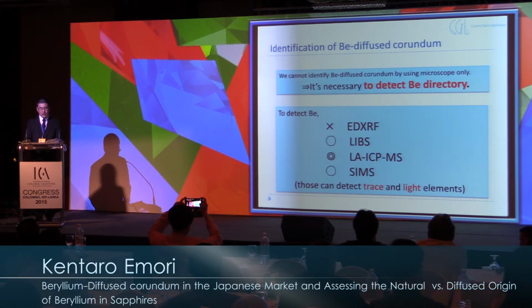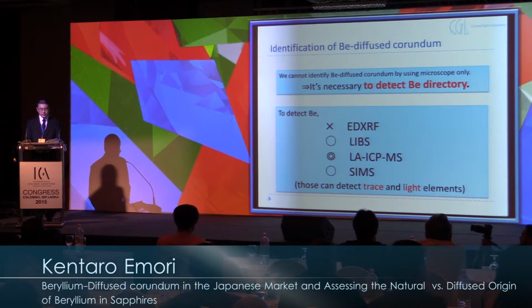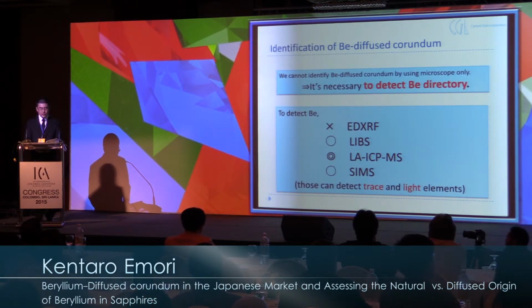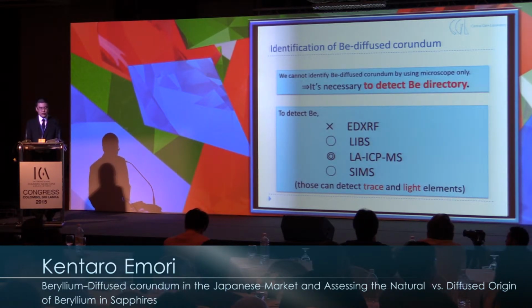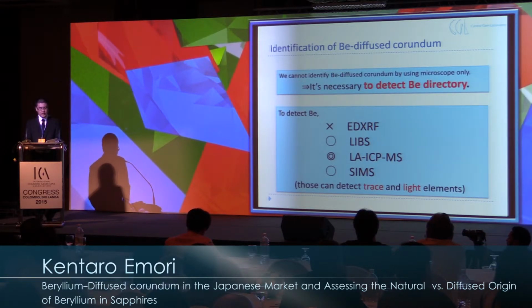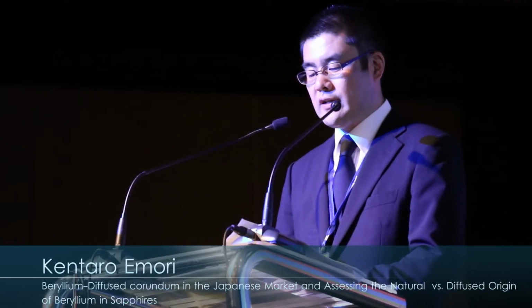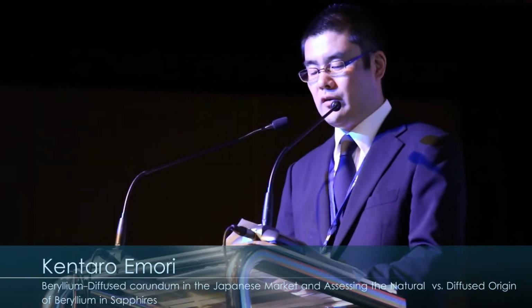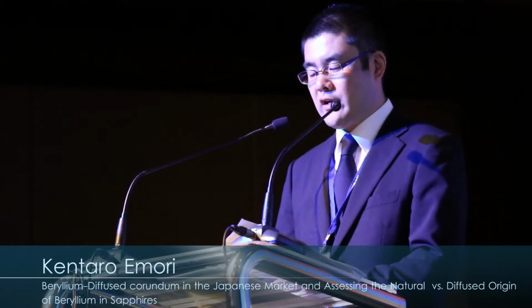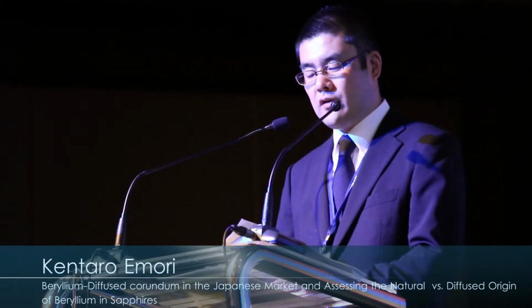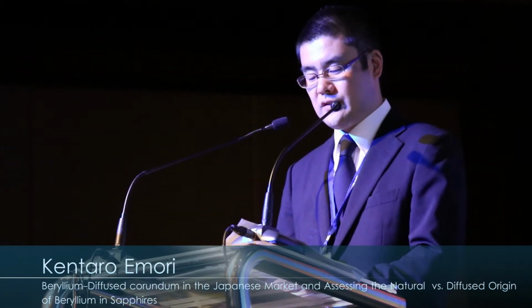Beryllium-diffused treatment cannot be identified by eye observation if the conformal layer or unique inclusion is not visible. Therefore, we must analyze beryllium directly. EDXRF, which is used widely in the gemological field, cannot detect beryllium, because beryllium is a light element and diffused in lower content. To detect beryllium, we need LIBS, LA-ICP-MS, and SIMS. Those can detect light elements with high sensitivity.